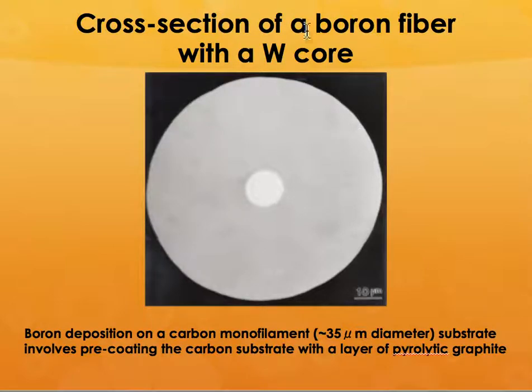This shows the cross section of a boron fiber with a tungsten wire core. So the inside is a tungsten wire core, and the boron is uniformly deposited around it so that you get a perfectly circular fiber. Now, one thing to note here is this: this scale bar is 10 microns. So the whole fiber is approximately 100 microns or 0.1 millimeter or so. Compare that to carbon fibers. Carbon fibers are of the order of 5 microns or even less. It used to be about 7 to 10 microns, but now carbon fibers are made at a diameter of 5 microns or less.